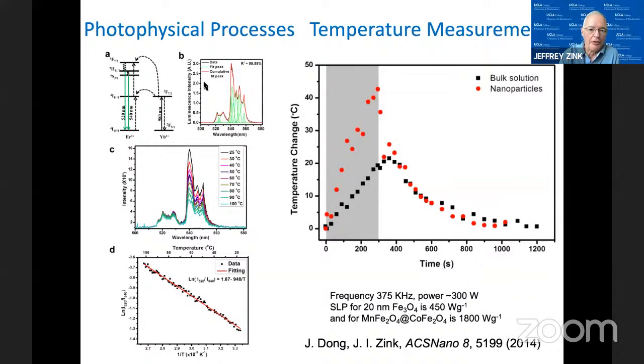The thermometer works because two excited states are in near Boltzmann equilibrium with each other. So the ratio of the populations of those states is going to be related to the temperature. We can look at the emission spectrum and get a working curve, put them in known temperatures and look at the ratio of those. And from that working curve, determine the temperature inside our nanoparticles. And when we do these experiments, we find on the right-hand side of this thing, the bulk solution, of course, does heat up, but the internal temperature is much higher than the overall bulk temperature. And that's going to be a key because we can use that local nano internal temperature on the particle to release caps without necessarily overheating the overall bulk system.